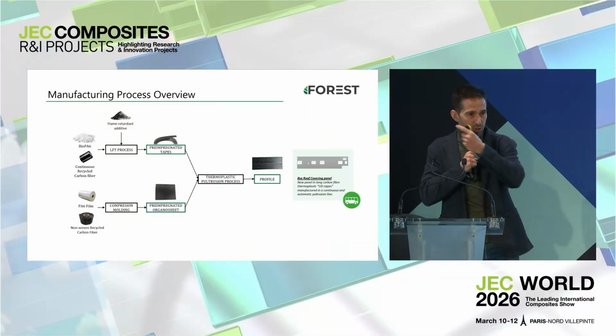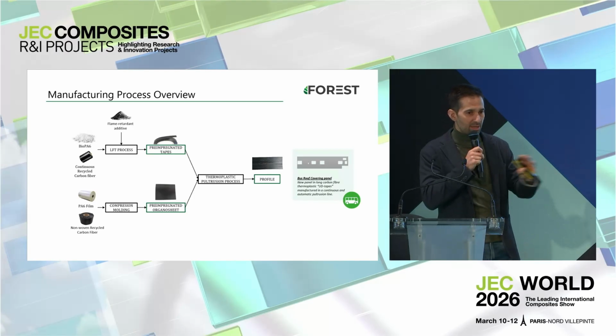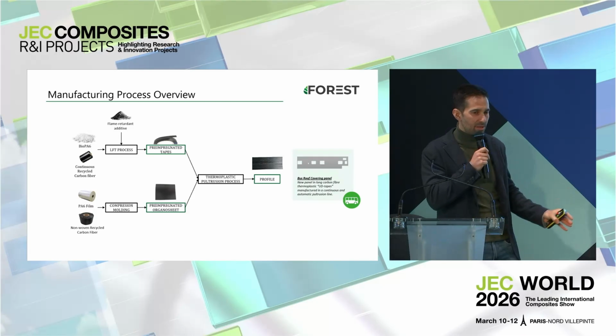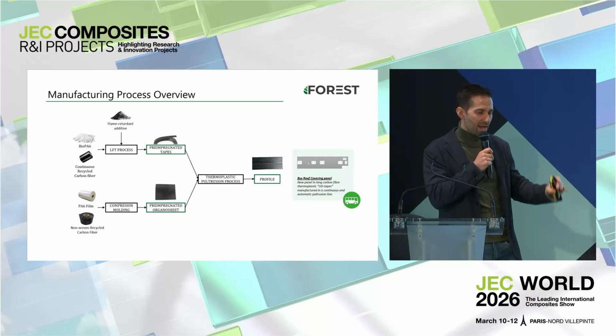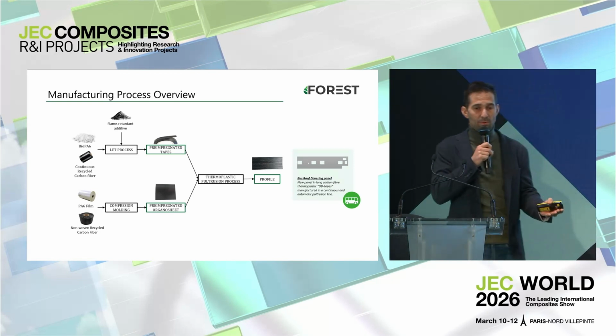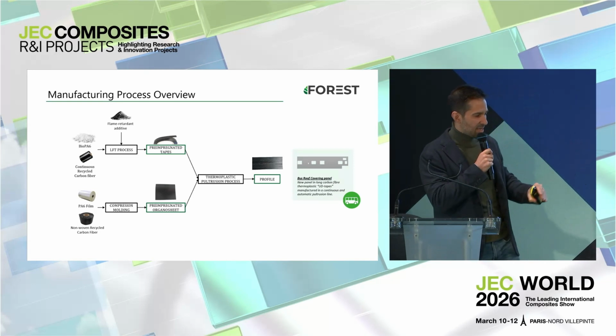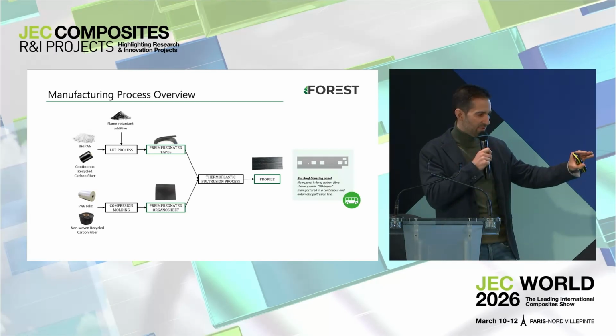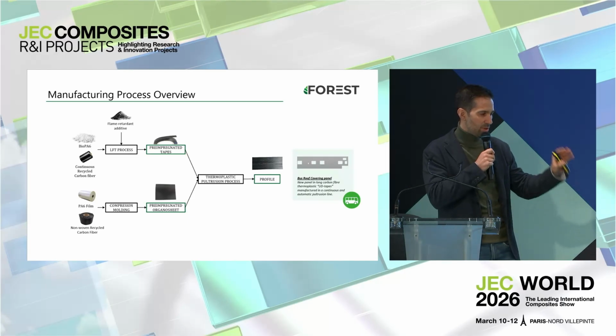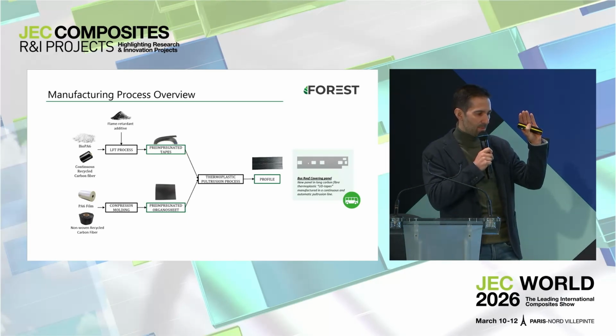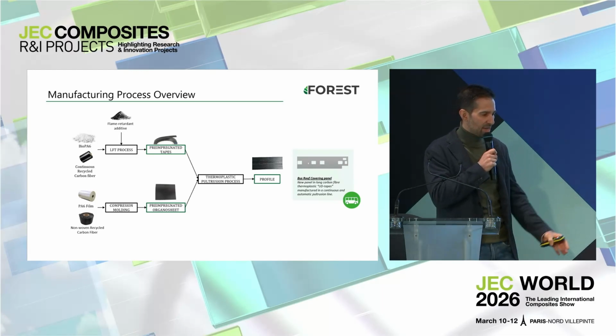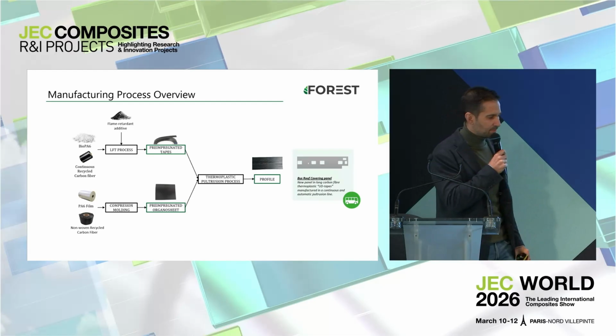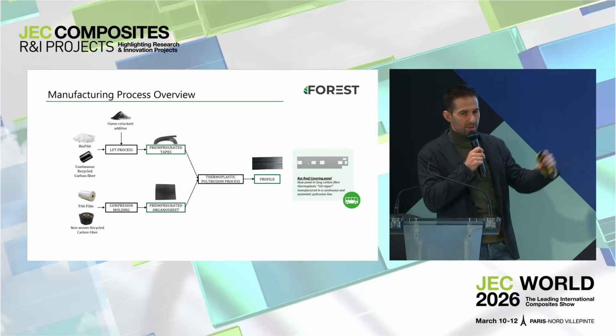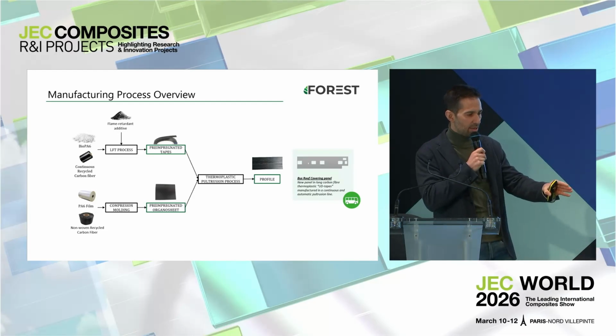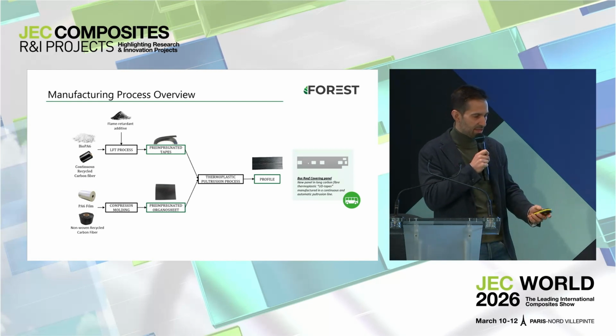And for this specific demonstrator, we needed better properties in the transversal direction. So we decided to make a hybrid, incorporating an inner core layer of non-woven recycled carbon fiber as well. For this step, we included an additional step of manufacturing an organosheet made with non-woven and biopolyamide film, in this case by a thermolaminating commercial equipment. And then we use these organosheets together with the UD tapes in a thermoplastic pultrusion process to manufacture the flat profile of this hybrid laminate for the bus demo.